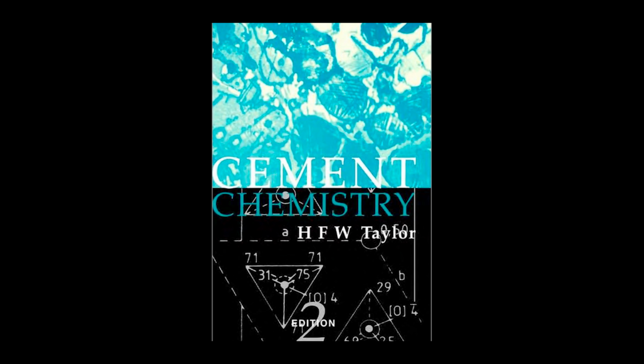ASR expansion generates microcracks and internal stress fields. Essentially, the ASR damage precedes the symptomatic formation of the secondary ettringite. The expansive gel from ASR provides the localized internal space and the chemical pathways that are required for the delayed ettringite to crystallize later, often forming visible veins in those pre-existing ASR cracks and at the aggregate paste interfaces.